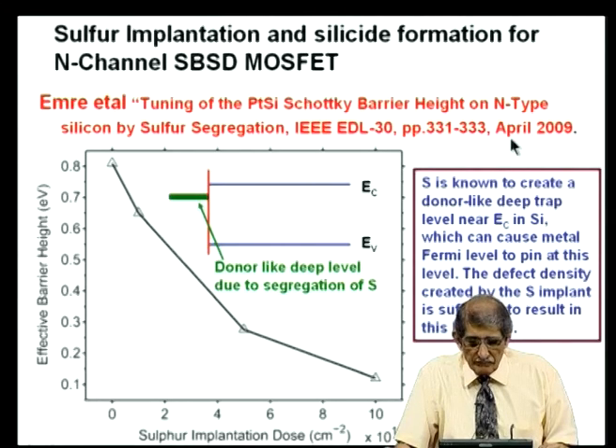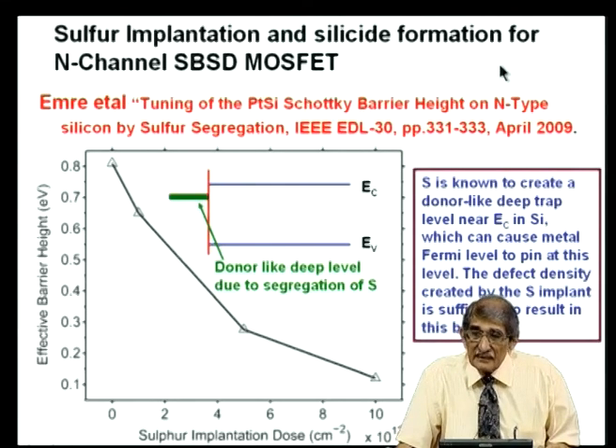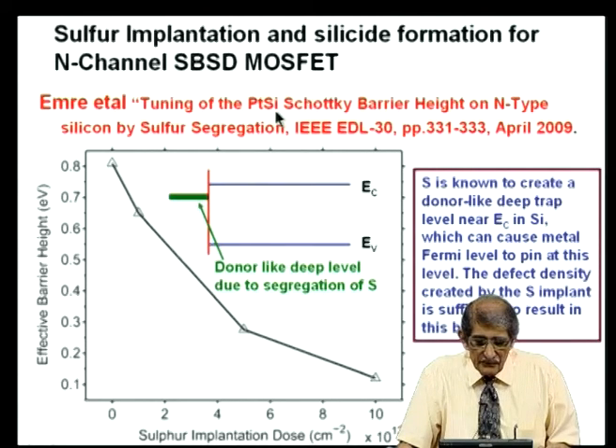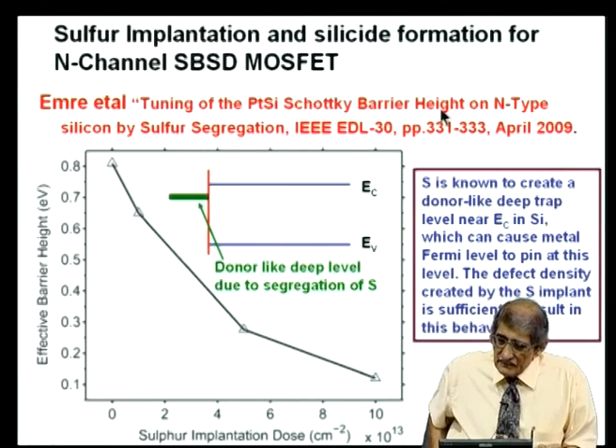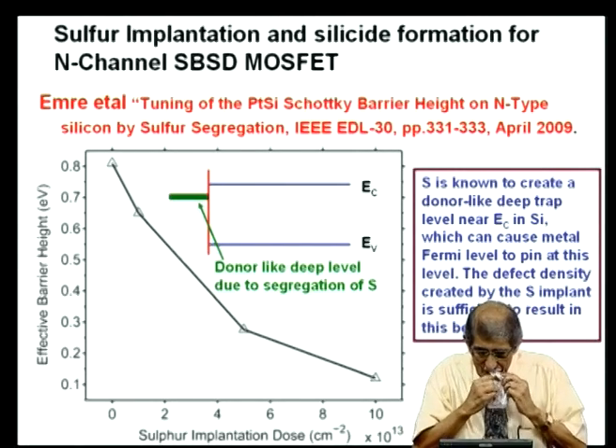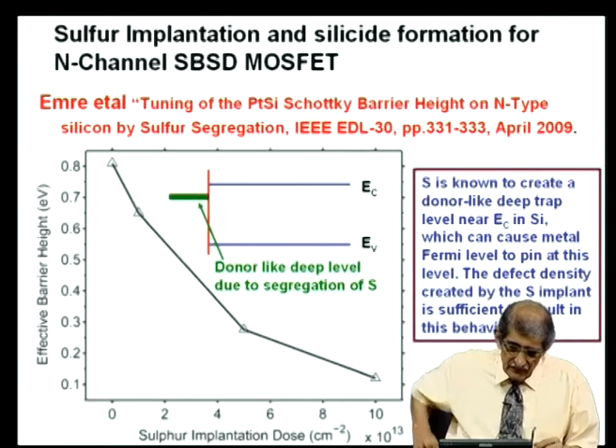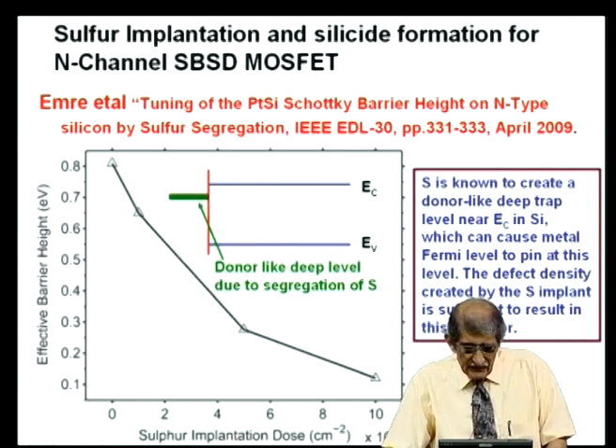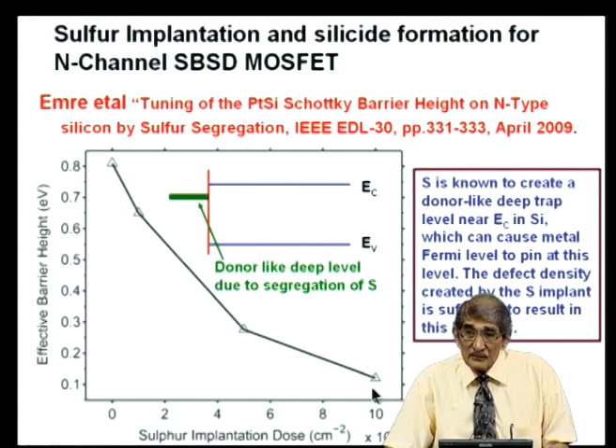Okay. So, this is one of those papers which appeared in 2009. Schottky barrier source drain MOSFET, sulfur implantation and silicide formation for n-channel devices. Tuning of platinum silicide Schottky barrier height on n-silicon by sulfur segregation. So, sulfur implantation dose, per centimeter square, 2, 4, 6, 8, 10 × 10^13 per centimeter square.